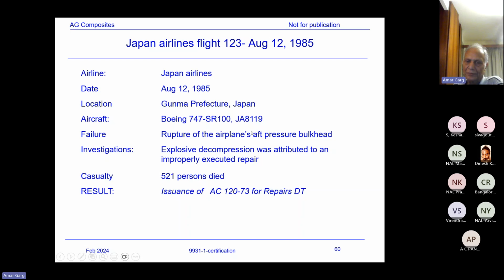Then Japan Airlines. Now, this is important. Somebody asked a question, how did the damage tolerance amendment come into the picture? So the history is related to this Japan Airlines flight. The rupture of the airplane's aft pressure bulkhead, the explosive decompression, was attributed to an improperly executed repair. The repair which was performed was not properly done. And so it led to 521 persons dying, the worst air disaster in the history of aviation,